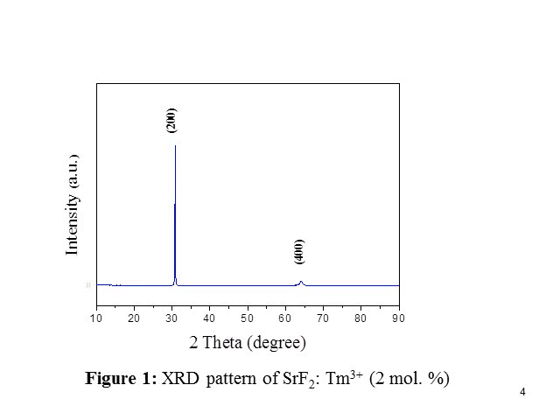We first studied the SrF2 single crystal by X-ray diffraction. The diffractogram in question mainly shows a single intense diffraction peak identified as corresponding to the diffraction on the reticular planes 200. This reflects the fact that this direction is favored during crystal growth.